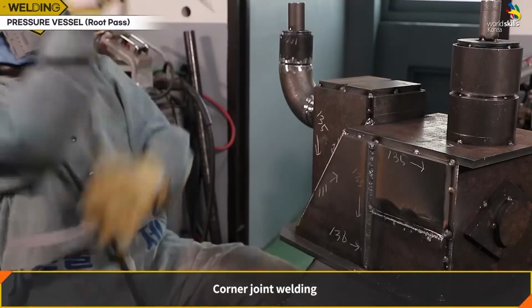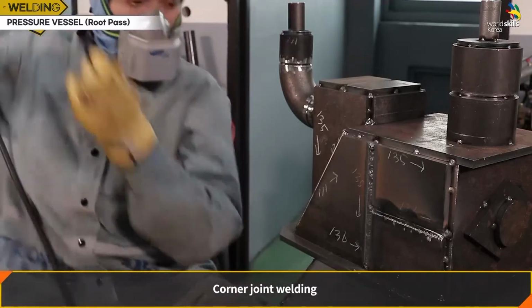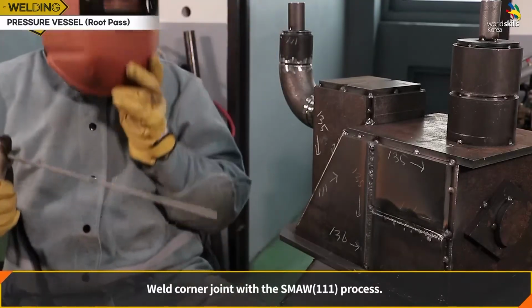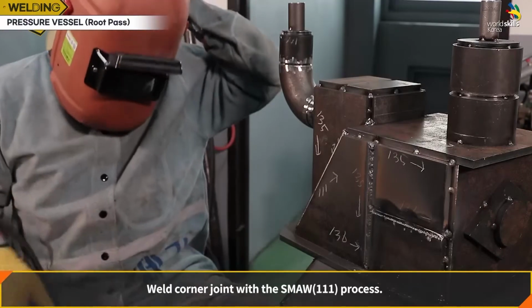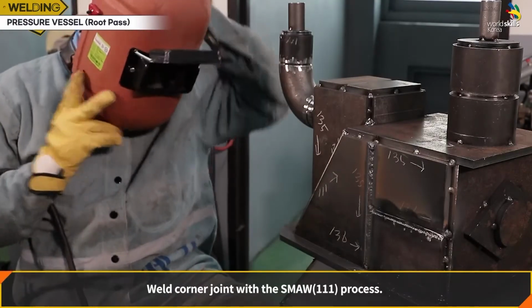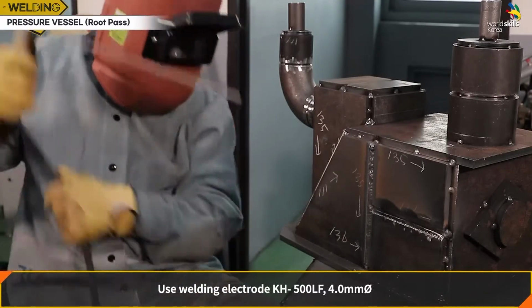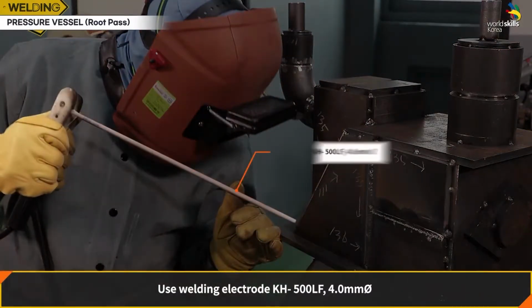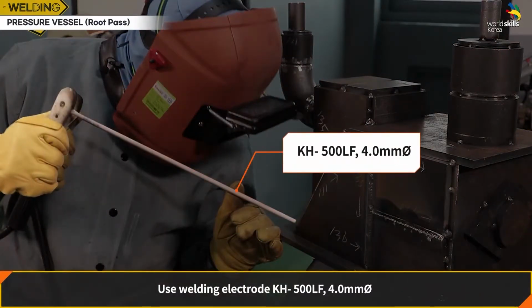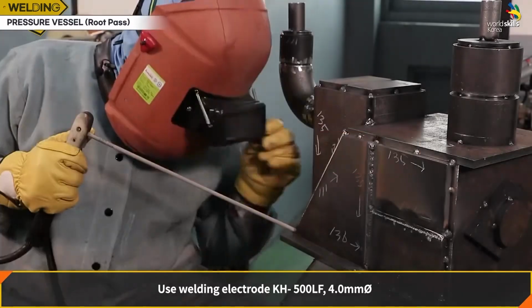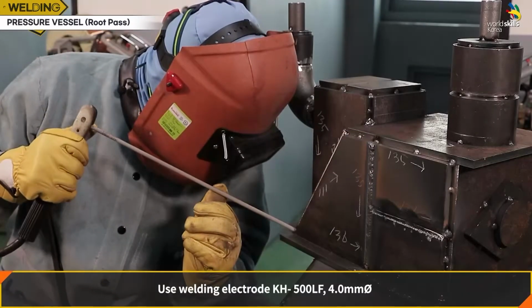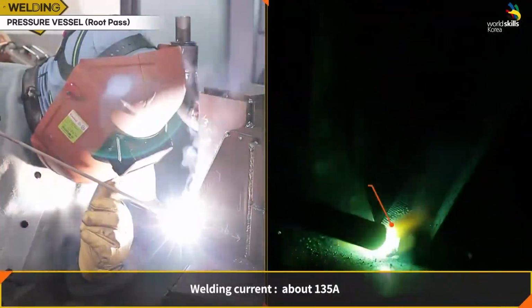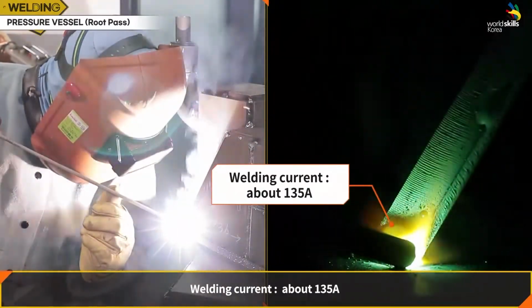Corner joint welding. Weld corner joint with the SMAW 111 process. Use welding electrode KH500LF 4.0 mm. Welding current is about 135 ampere.